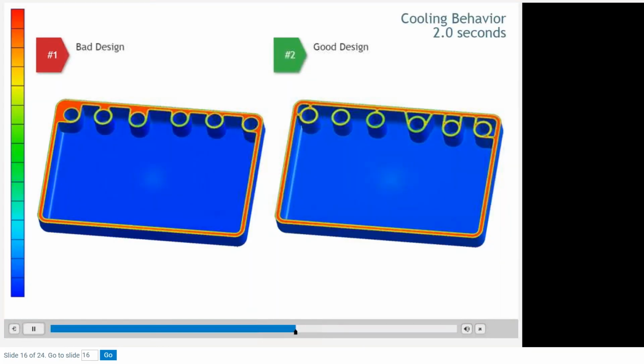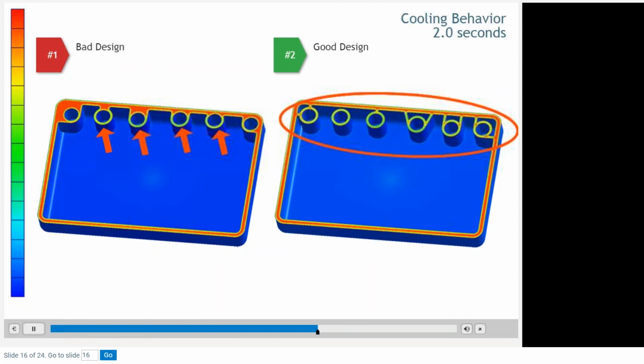Let's look at the cooling behavior for both boss designs by examining the temperature during the packing and cooling phases at time intervals of 2, 8, and 16 seconds, and the end of packing at 25 seconds. Starting with the 2-second interval, here you can see the temperature distribution in a cross-section of the two designs. The nominal walls of both parts remain at a higher temperature, but the first image clearly indicates where the thicker sections kept their heat. The thinner boss cross-sections on both designs show a rapid heat loss.